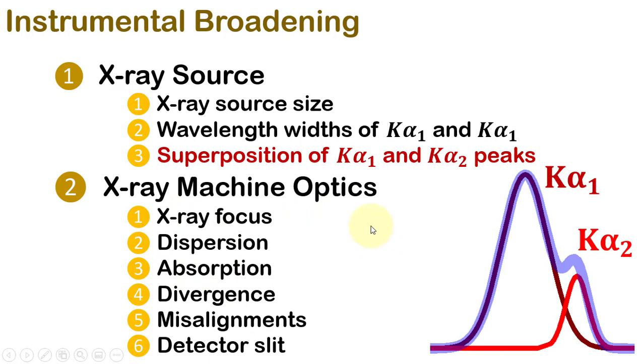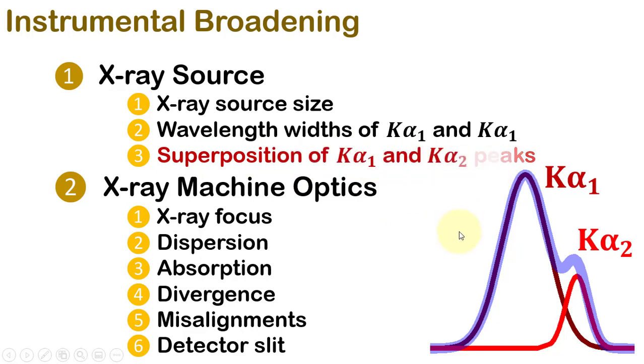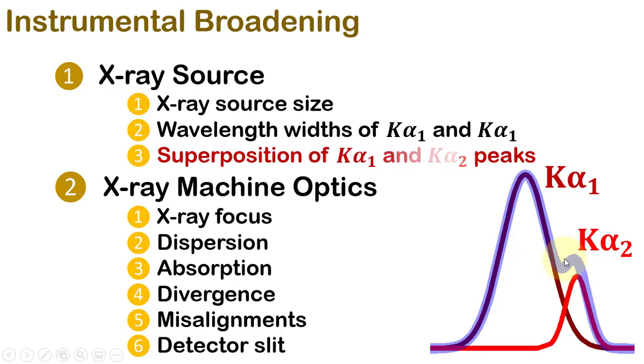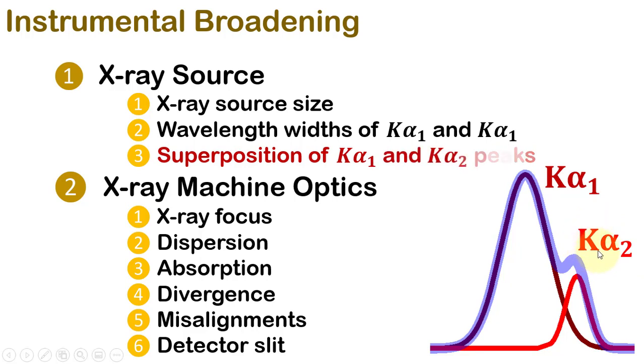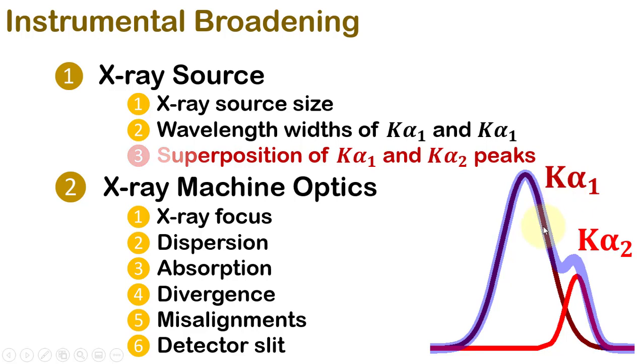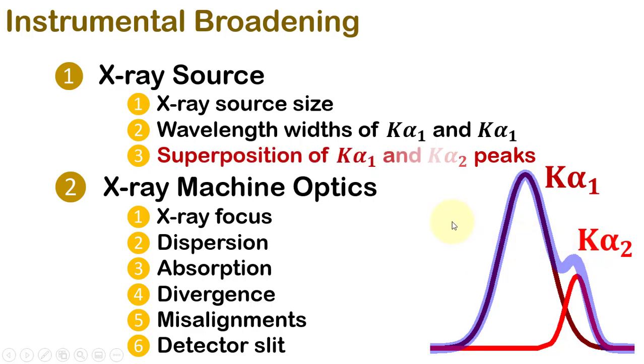However, in this video, we will only discuss the broadening caused by the superposition of Kα1 and Kα2 peaks. When in the X-ray peak, this kind of branch or shoulder occurs and which is consistent with all the peaks as well as becomes prominent within increasing 2θ values is actually due to the superposition of Kα1 and Kα2 peaks. In order to calculate only for Kα1, we will have to deconvolute the composite peak into 2 to calculate the exact parameters from the diffraction pattern.